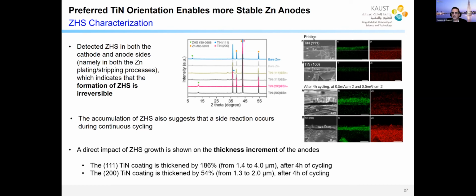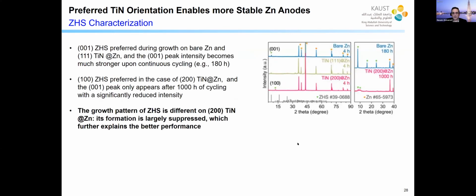The titanium nitride, before we cycle the samples, is about 1.3 micron here, about 1.4 micron here, the same thing. After you cycle, look, the 111 titanium nitride becomes 4 micron thick. So there's a lot of byproduct forming. In the case of the 200 titanium nitride, it has a thickness of 2.0, roughly half. So there's less of it forming, and you can see that also in this chart here.